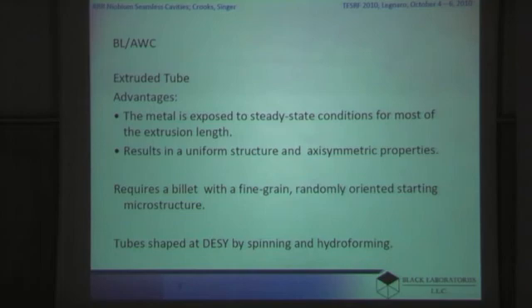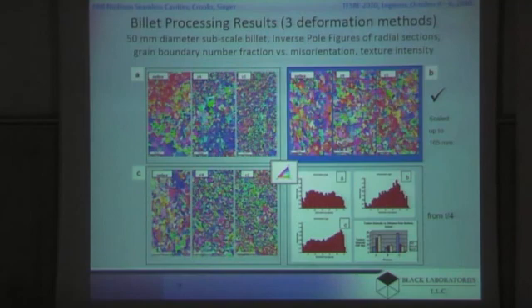To do that, we spent a lot of effort on looking at the effects of severe processing of the bulk material and recrystallization processing, and produced a fine uniform billet. I'll just show you a little bit of the microstructure of the different methods we tried. Method on the left gave us an extremely fine interior, but after recrystallization, this was in a small billet diameter of 50 millimeters, and the structure coarsened and also showed texture banding here, which happens in niobium under some circumstances of severe deformation. The second process here is the one we ended up choosing and showed the most uniform structure, and a third process also showed a non-uniform structure.